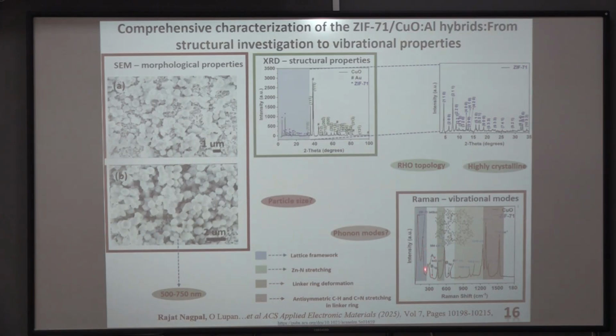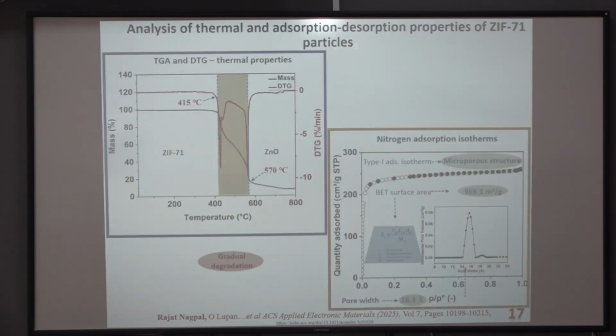starting with the blue regime at low wave number, which is associated with the lattice framework vibrations, followed by zinc nitrogen stretching, and in the yellow regime, linker ring deformation phonon modes, and at high wave numbers, antisymmetric stretching vibrations in the linker ring.